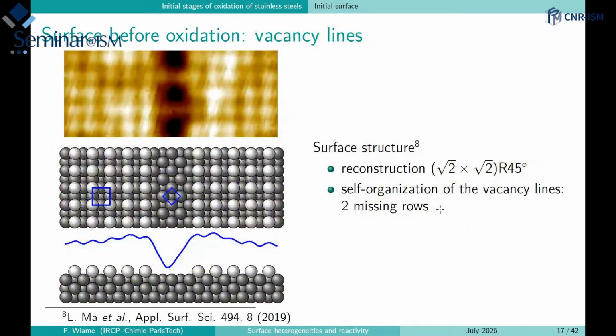So the model we can make: you can see that we have the root 2 reconstruction here, this is the 1 by 1, and you can see the rows of atoms from the top, and here from the side view, this is an STM profile, where we can see these 2 missing rows here. And as I said, these vacancy lines, so these 2 missing rows, are periodically aligned, which may seem strange, but in fact, this self-organization is quite common.